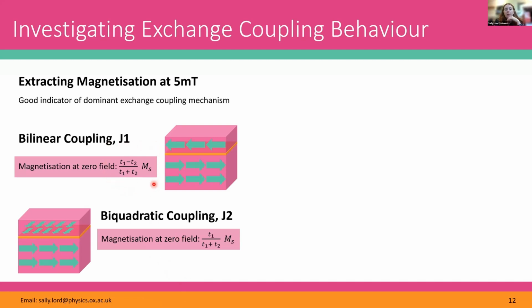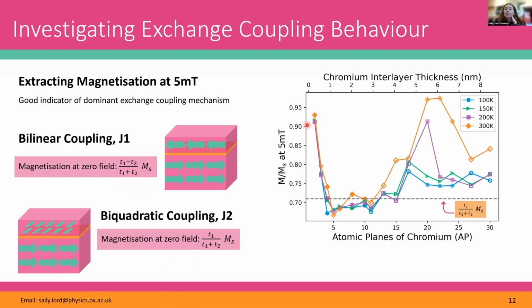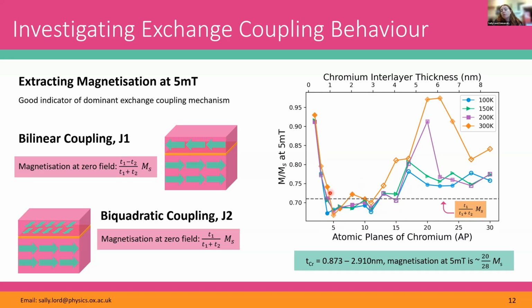So the magnetization at zero field for the two types of coupling is given by these values here. We extracted the magnetization at 5 millitesla, and here is plotted the relative magnetization, so that value divided by the saturation magnetization. And this gray line here is the value that you would expect if you had dominant biquadratic coupling. What you can see is that for the range of chromium thickness values, the relative magnetization at 5 millitesla is close to this value, which implies that perhaps biquadratic coupling is the dominant coupling mechanism in our system.